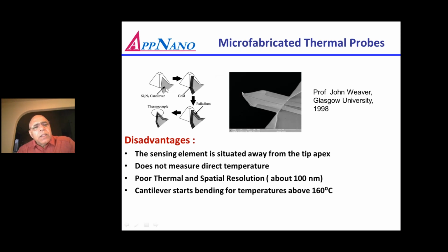So after patterning the silicon nitride cantilever, the two metals are coated, so eventually you get this palladium-gold thermocouple over here at the end. The biggest thing to realize is that when you make this, the sharpness of the tip is decided by the thickness of the nitride. Secondly, the thermocouple is away from the apex. It has to be inside here, where the cursor is, so it has to be a little bit below the apex. So when you are scanning, you are scanning with the nitride tip and not the thermocouple, so it is away from that.